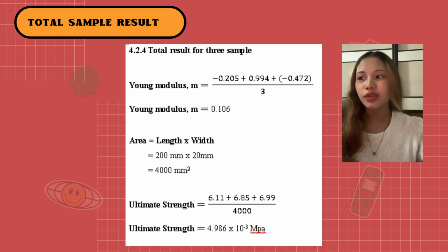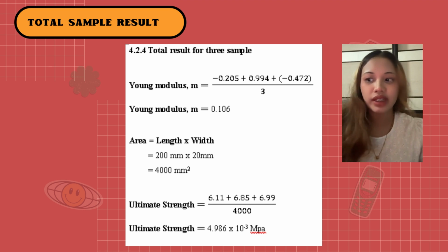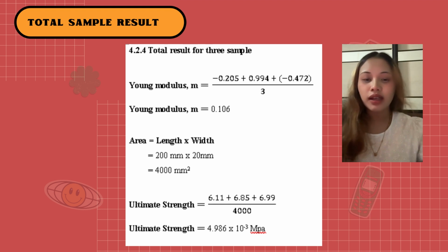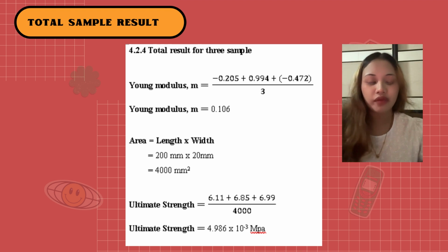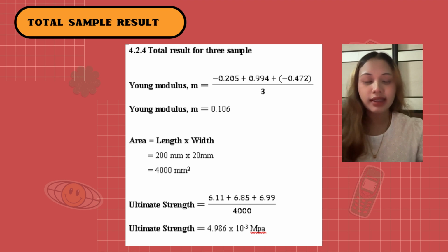Last but not least is the total sample result. For Young modulus, average is negative 0.205 plus 0.994 plus negative 0.472 divided by 3. So the total average for Young modulus is 0.106. The area, 200 millimeter times 20 millimeter, we got 4000 millimeter square. And the last one is ultimate strength, 6.11 plus 6.85 plus 6.99 divided by 4000. The total for ultimate strength is 4.986 to the power of negative 3 MPa. That's all for the calculations part, and that's all from me. Thank you.